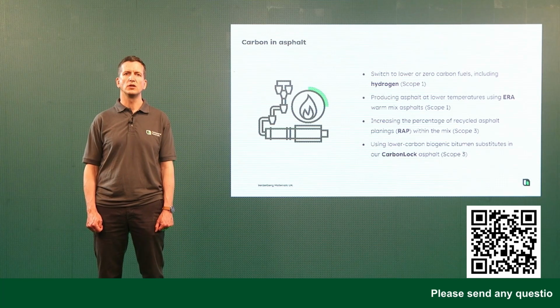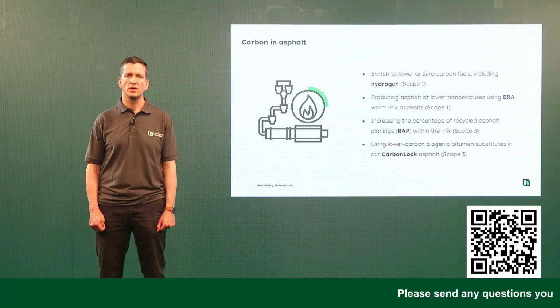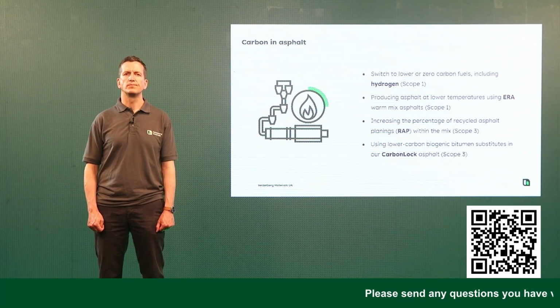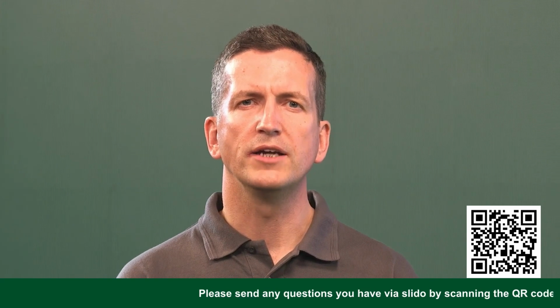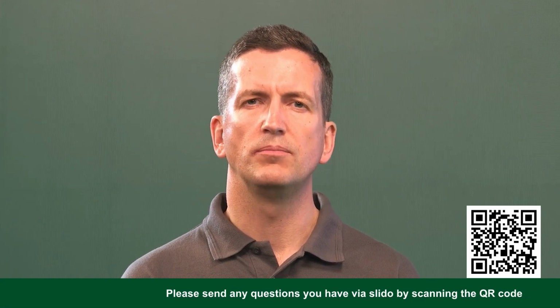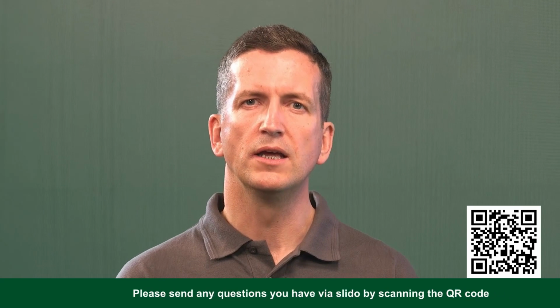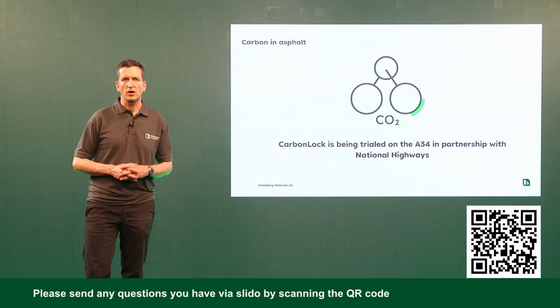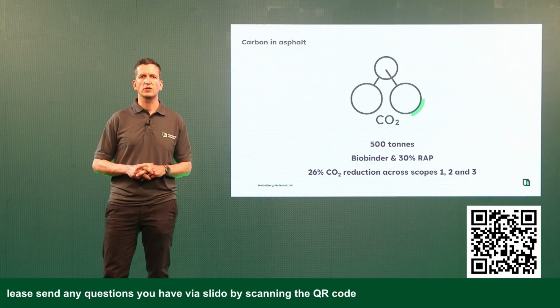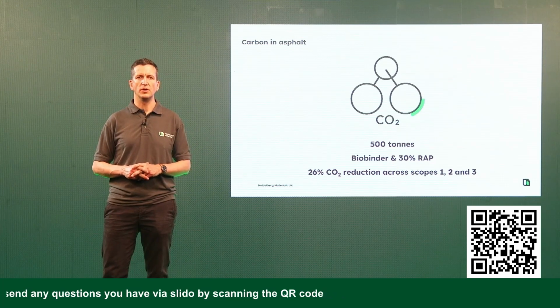Following our success in 2023 of our A30 trial with the first use of a biobinder asphalt in a thin surface course on the strategic road network, we're now moving to phase 2, working collaboratively with National Highways and Atkins. We're undertaking further trials on the A2 and A34 using a polymer modified biogenic binder in combination with our ERA 140 asphalt mix, and importantly, a recycled asphalt planings content of 30% in a thin surface course. This high wrap content material will use Shell's Carafalt Ultra Carbon Sink biobinder.